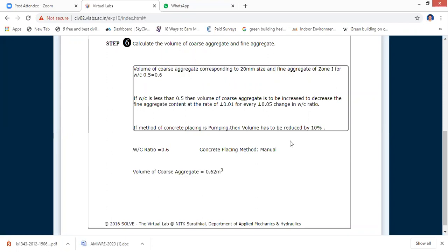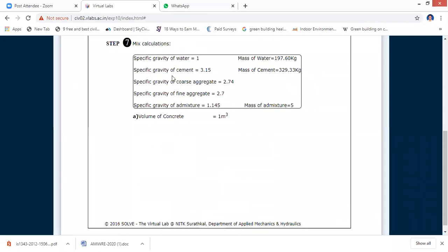Okay, so it's given all the values, and water cement ratio is 0.6. Volume of coarse aggregate is 0.62. Volume of fine aggregate is 1 minus volume of coarse aggregate, which is 0.38. We all know this. Why? Because it's 1 cubic meter. In that, we have to subtract all other values. Then this is the mix calculation.